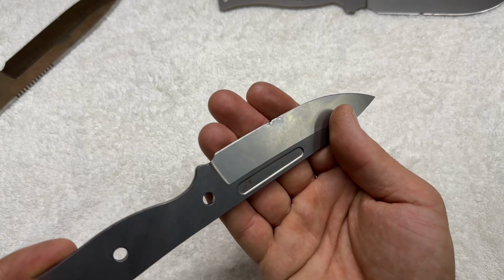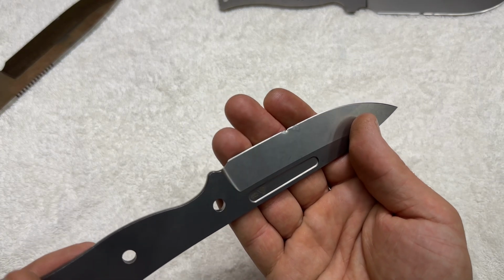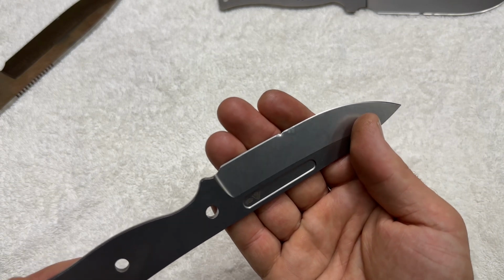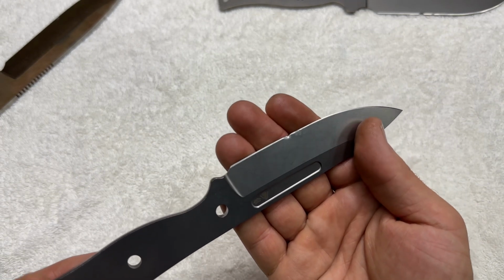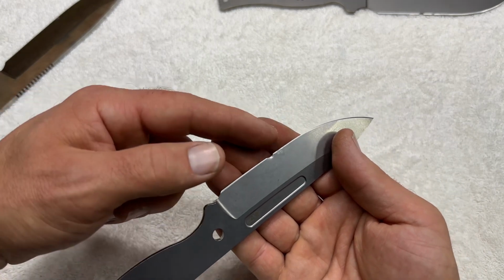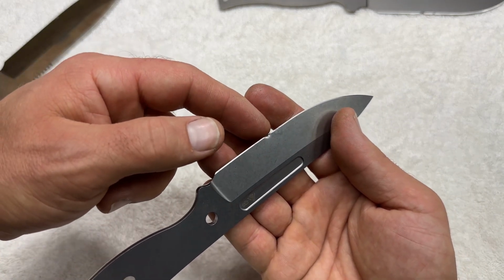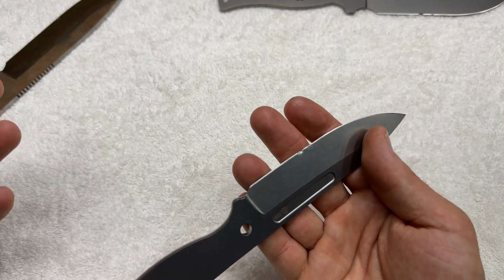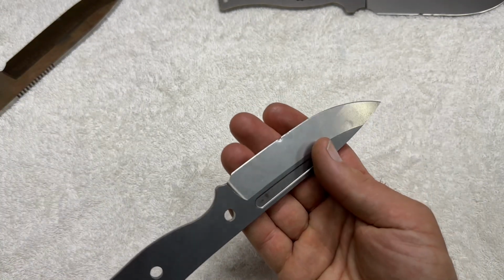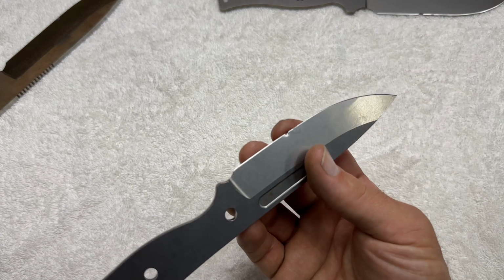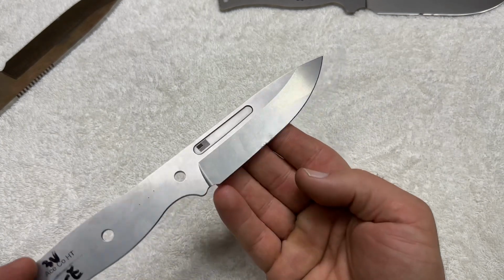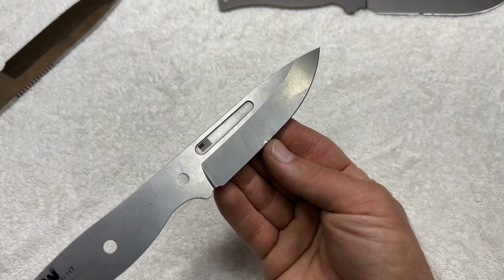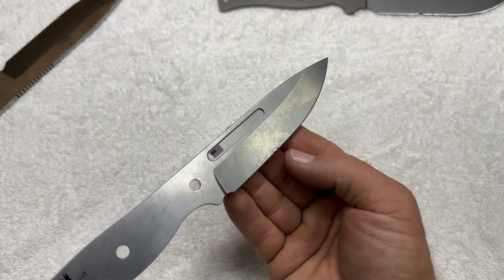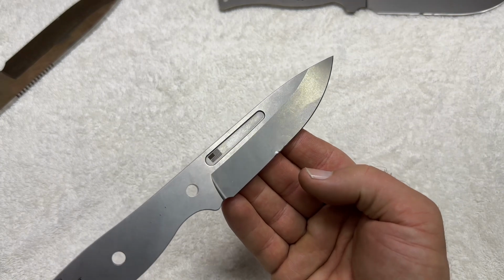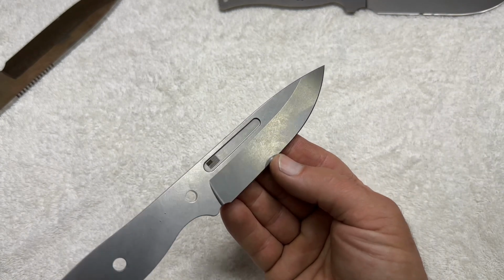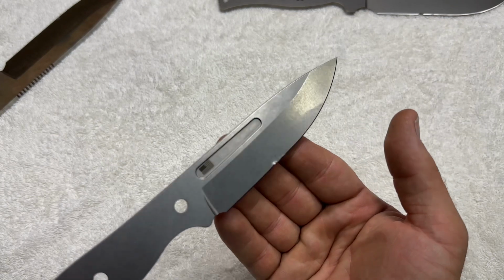So other than a couple of knives I've made in the past, way back in 2012, 2013, for people that knew what they were getting with the 3V knife, just for woodworking, things like that, it's phenomenal. But when you get into the side loading where you want to be doing heavy batoning, or you might be hitting something harder than wood, rope, leather, things like that, if you have a mixed use case with a Scandi, the apex is going to want to fold over just due to that toughness disparity between the longitudinal and transverse toughness. So when you look at those transverse values, there's actually a lot of stainless steels on the market that handle that side loading a heck of a lot better, and they're easier to resharpen than something like 3V.